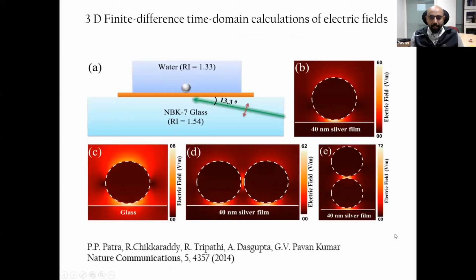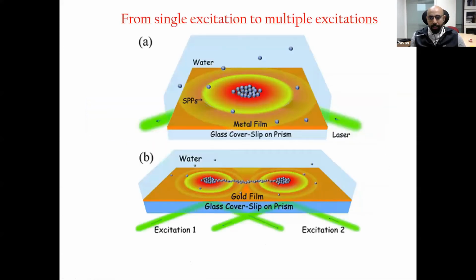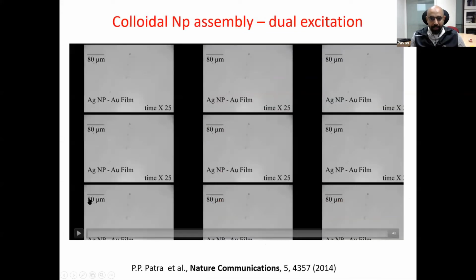Associated with this are also very interesting optical electrodynamic kind of characteristics. There is the hotspot, what I was talking about, which I started with, can now also be facilitated between particle and the film. It can also occur between particle and the particle, and there can also be hotspots created between the particles which are stacked in the z direction. This provides some very interesting opportunities for manipulation of optical fields. You can now extrapolate this not only from one excitation, but to multiple excitations. So you actually can go from one single excitation to many excitations. And such excitations can lead to some interesting opportunities.